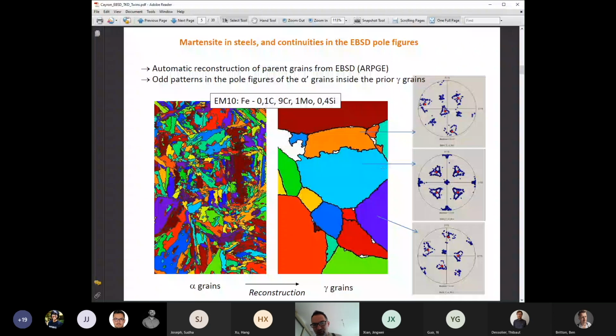So I plotted the pole figure on the right. They are represented in blue, the experimental pole figure of the variants. And instead of getting discrete spots coming from the 24 variants, I obtained continuous features. I don't know if you see them, like threefold flowers and a little cross. If you had only 24 variants, you would not get these nice continuous features in the pole figures. So everything started from this simple question: how can I explain these continuous features in the pole figure of martensite?